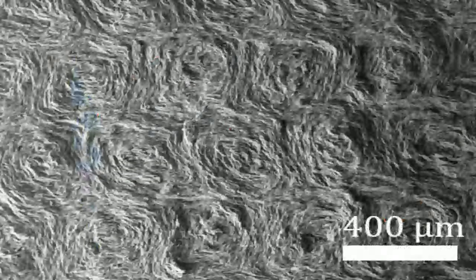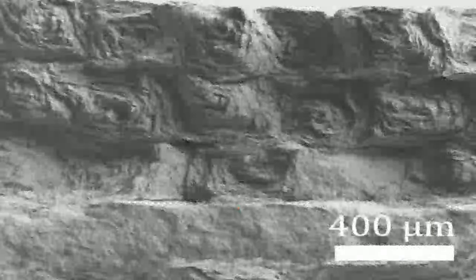The fibers got damaged? Exactly. The carbon fibers, the very things providing the reinforcement and toughness, reacted chemically with the surrounding ceramic matrix components or with the sintering additives needed to densify the ceramic. What kind of reactions? Well, for example, in an alumina matrix that used yttria as a sintering aid, the fibers were basically consumed, reacted away.